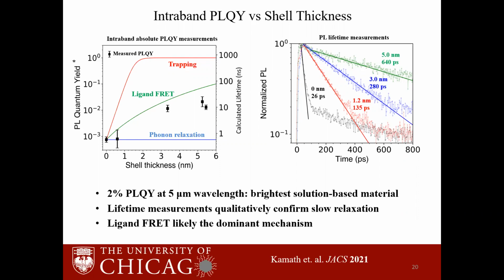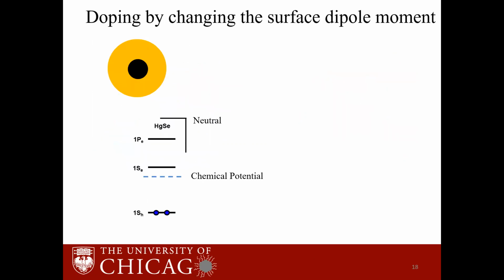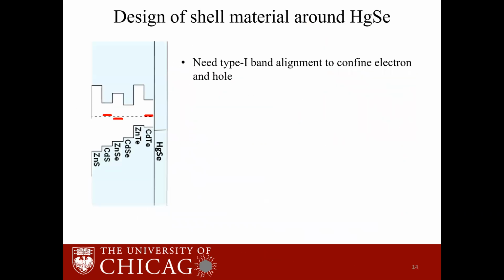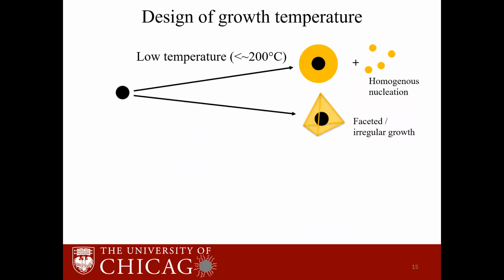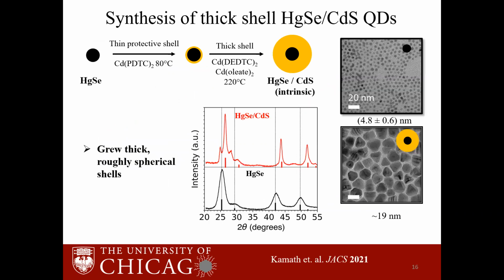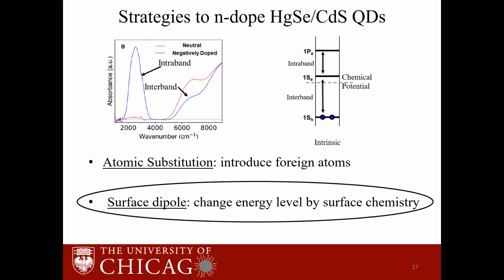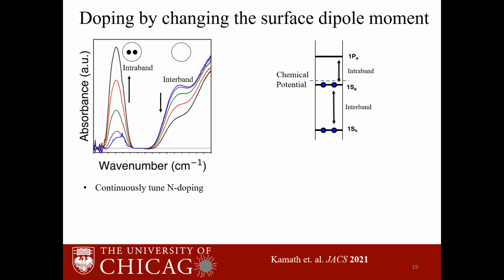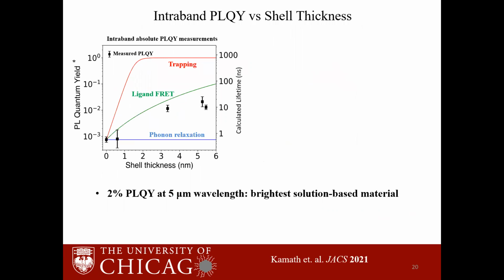It might also be due to the fact that our shells are not entirely spherical. So it's not a very precise model. But we believe that if the problem of the defects is solved, then you should be able to go to brighter quantum dots if you go to a thicker shell.